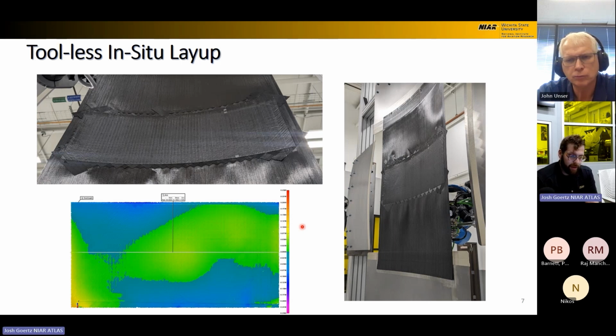This is still very much in research technology here, but there's some promising results as far as part accuracy. This gray line is fitted to the curvature of the part here, and it came out to a 51.78 inch radius compared to a 50-inch nominal. So you're seeing a similar level of spring back that you see when laying up on a tool, as far as a couple of degrees of spring back.